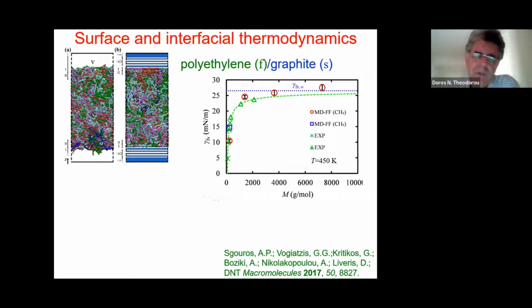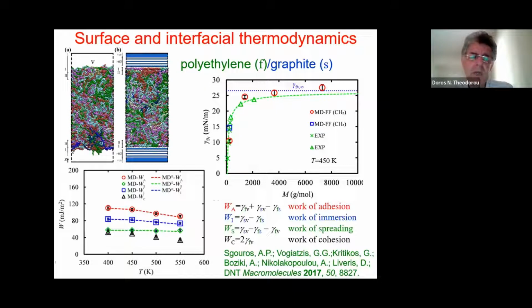When you increase the molar mass of a polymer melt, you increase the surface tension until you reach a pretty much asymptotic limit, which is at this temperature on the order of 26 millinewton per meter for the polyethylene, and it is not too badly predicted by the simulation. If you do similar things to calculate the adhesion tension, you can also calculate thermodynamic properties for the interfaces: work of adhesion, work of immersion, and work of spreading. These are functions of the interfacial tensions for polymer-solid, polymer-vacuum, and solid-vacuum. And here they are shown as functions of the temperature with the corresponding points. The work of adhesion is the red points, for example.